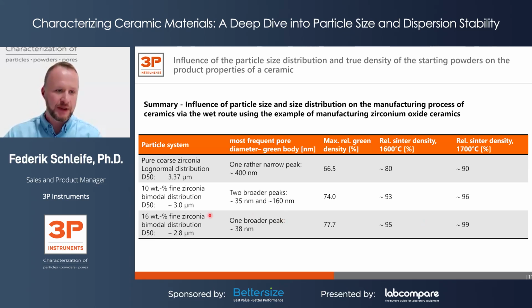And finally, when you use 16 weight percentage of the fine zirconia, we got a bimodal size distribution with a D50 of around 2.8 micrometer. We get one pore peak for the 38 nanometer pore radius, but we achieve really high densities either for green body and also for sinter bodies.